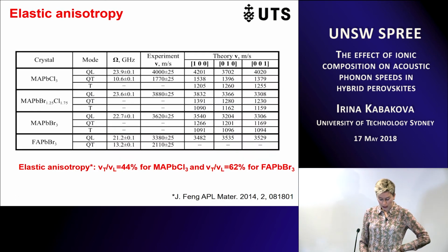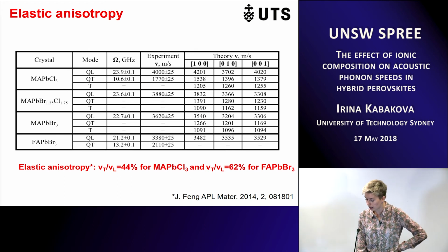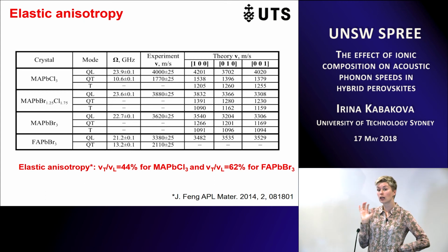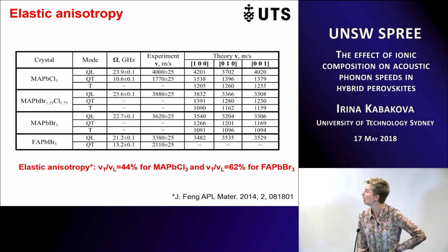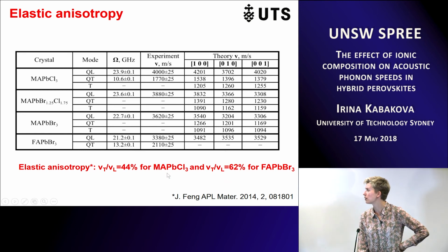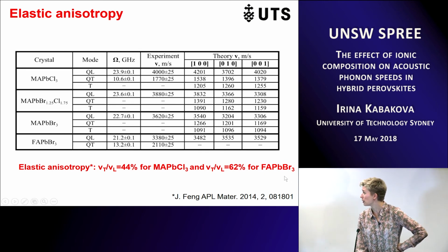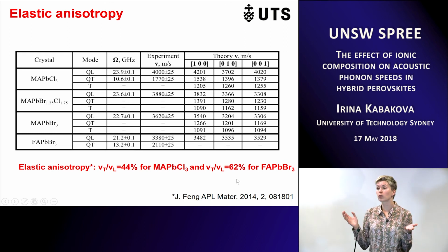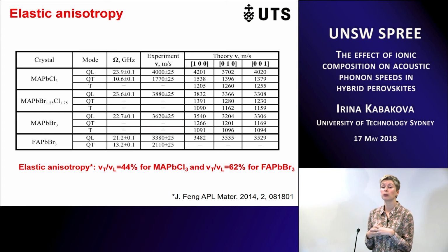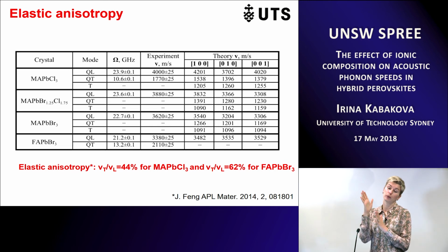organic molecules. The last little bit of discussion that I want to give is about elastic anisotropy in these crystals. It is quite usual for longitudinal waves to be faster than transverse waves, but in perovskites they're quite some faster than transverse ones. If you take, for instance, this crystal composition, then we find that the transverse wave is only 44% of longitudinal, and for the FA composition we have 62%. This has also been indicated in previous literature: elastic anisotropy, which means that these materials are quite susceptible to shear movements. Some of the authors do say that dynamic rearrangements can happen, and that they're quite soft for shear stresses and shear movements.